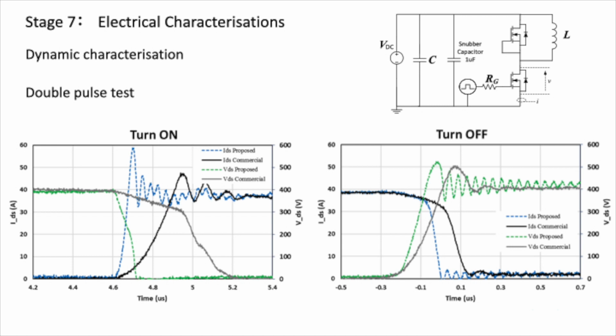one of these results compared with a closely rated commercial silicon carbide module. The dashed green and blue lines are the voltage and current of the proposed module, and the solid gray and black lines are from the commercial module. As you can see, the switching transient is much faster, and in terms of turn-off, it's similar. So now we know that the proposed module can switch much faster than the commercial module.